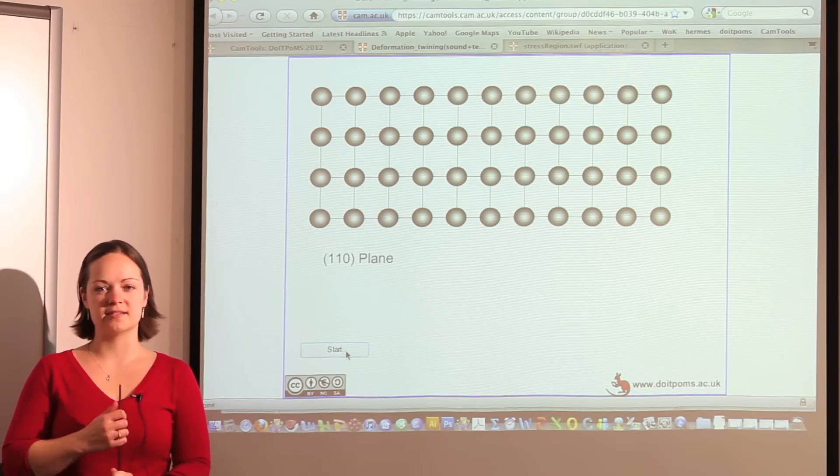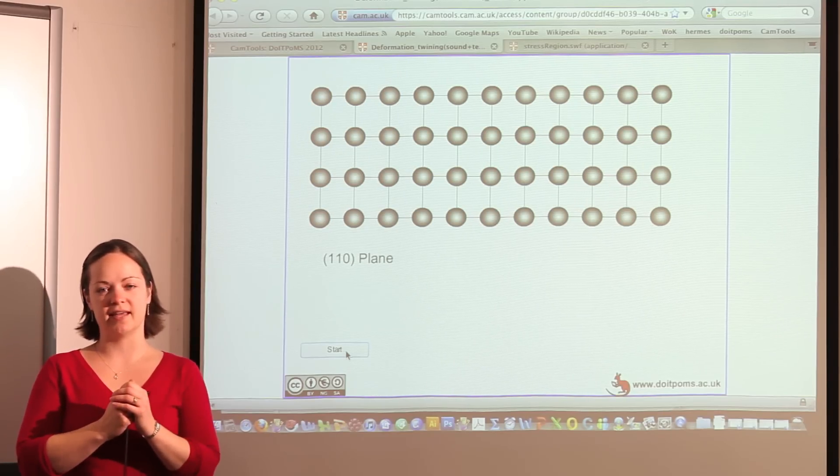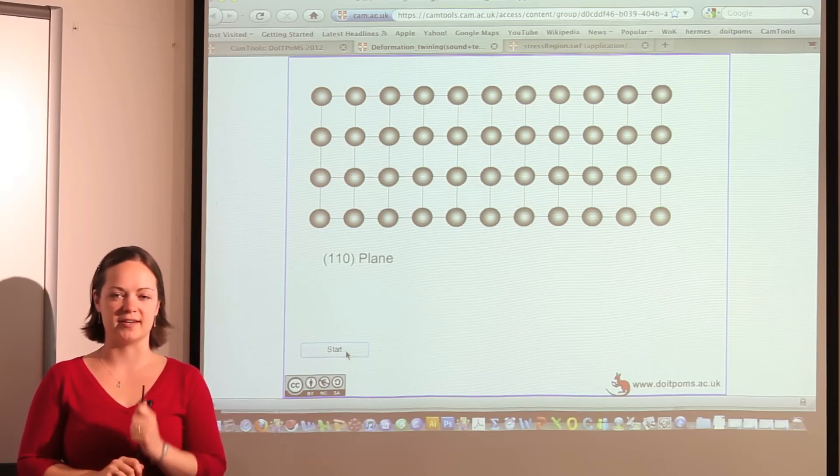The reason we heard this noise is because during deformation twinning the atoms move very rapidly all at the same time, which generates a sound wave.